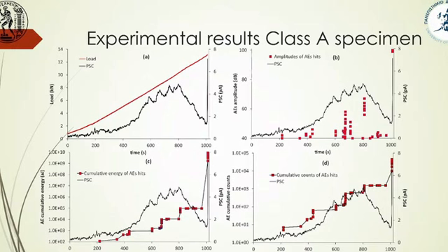This is in accordance with the recorded amplitudes of the acoustic emission hits, where we see that from the 600 second and afterwards, the acoustic emissions rise. The rise of the PSC follows the same trend as the acoustic emission hits.